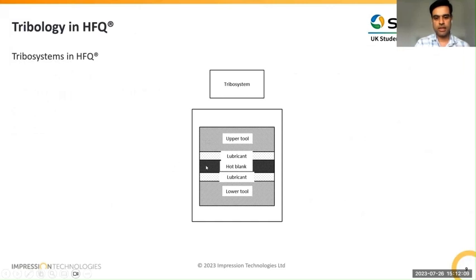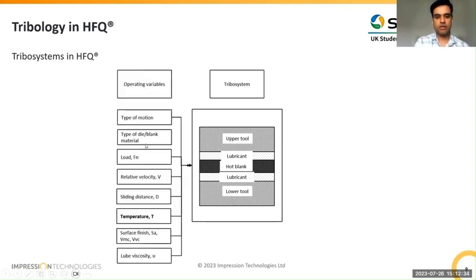So there's a hot blank in between, and then the upper and lower tool, which are going to form the part. In HFQ, we spray lubricant on the tool, so the blank does not come with any lubricant. And then the tools could be of tool steels, cast iron, or any other ferrous materials, which can also be coated with PVD coatings. And then there are a plethora of operating variables depending on what type of motion, type of blank, process parameters such as forming forces, sliding distances, relative velocity. More importantly, the temperature of the die and the part. And both the blank and the die come with a certain surface finish. And then finally, the viscosity of the lubricant. So there are quite a few operating parameters that influence the tribo system.